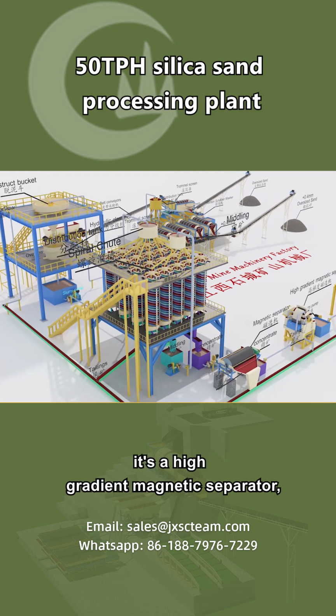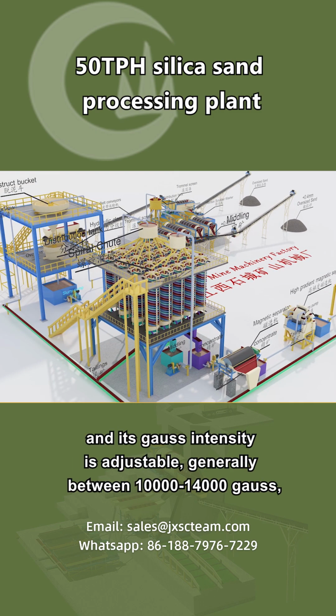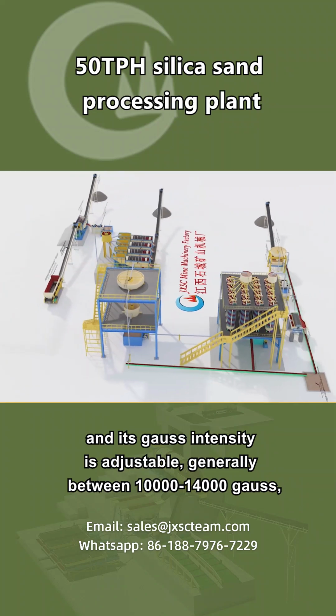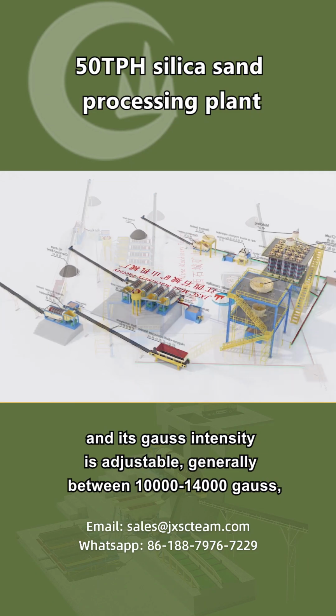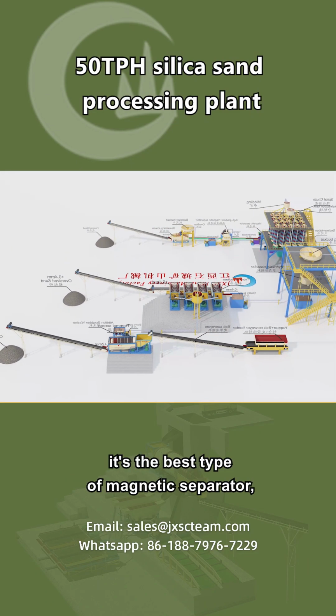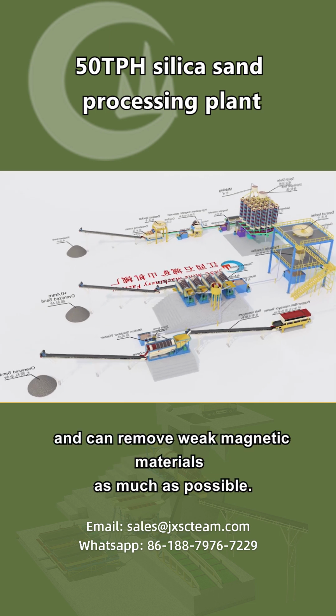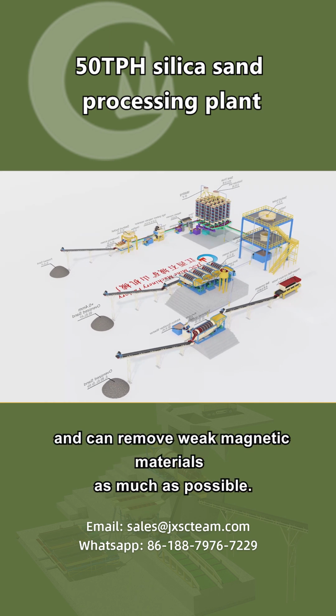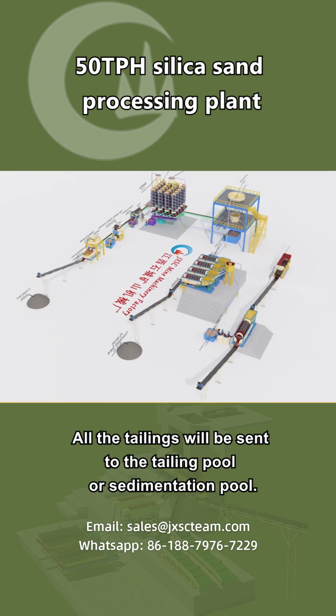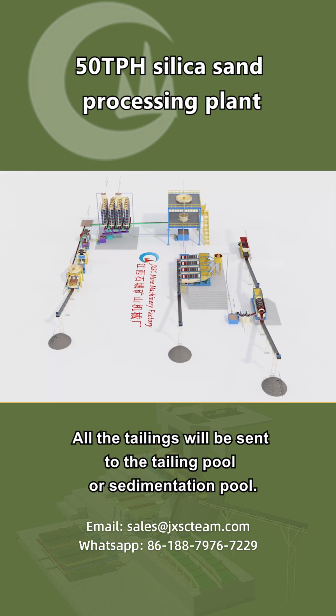It's a high-gradient magnetic separator, and its Gauss intensity is adjustable, generally between 10,000 to 14,000 Gauss. It's the best type of magnetic separator and can remove weak magnetic materials as much as possible. All the tailings will be sent to the tailing pool or sedimentation pool.